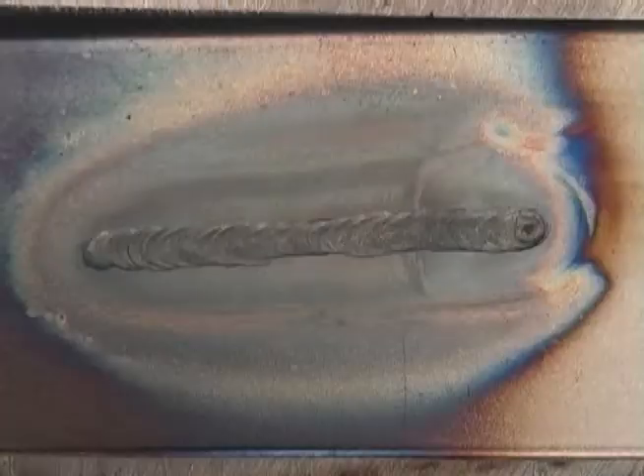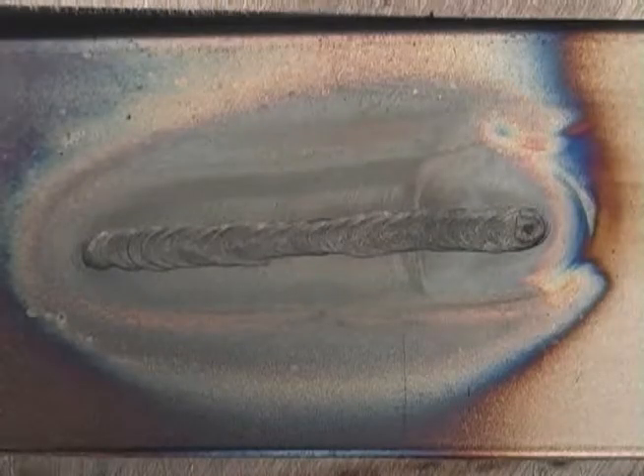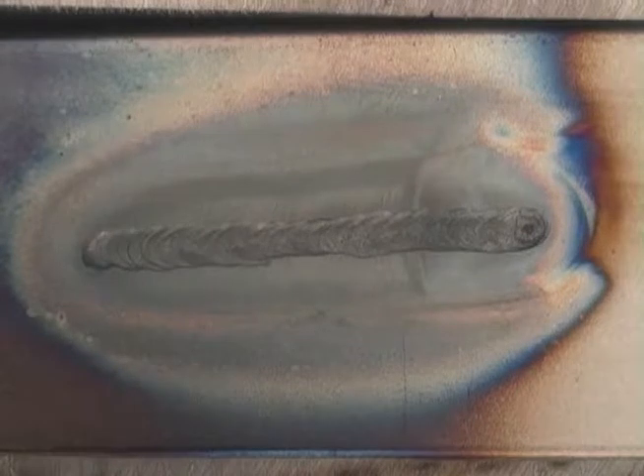You can see the finished weld has a consistent bead width with a nice row of dimes appearance. Again, the heat affected zone is relatively narrow and also consistent. Remember, melt the filler by dabbing it in the molten puddle. Do not try to melt the filler with the heat from the torch.